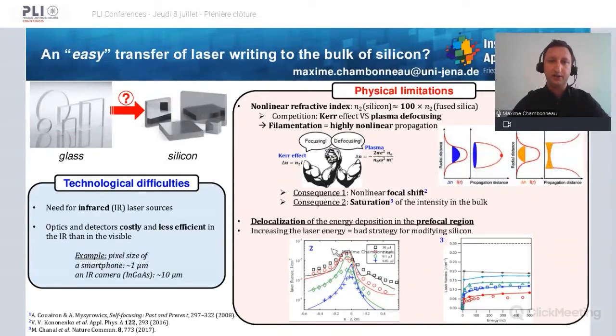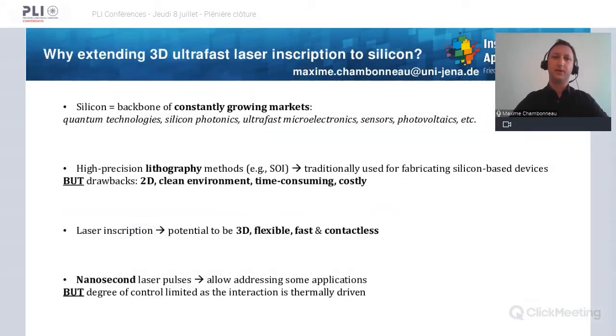First, as shown here, there is a nonlinear focal shift upstream of the laser when you increase the input pulse energy. And the second consequence is illustrated here. There is a saturation of the intensity inside the bulk of silicon. When you take those two consequences together, you can conclude that there will be some strong delocalization of the energy deposition in the prefocal region. Also, related to this, one can conclude that increasing the laser energy is usually a bad strategy for hoping to modify silicon. So why should we still try to push these limitations?